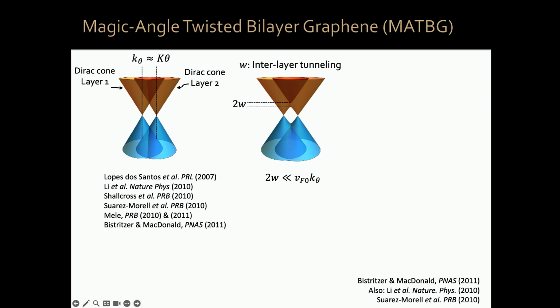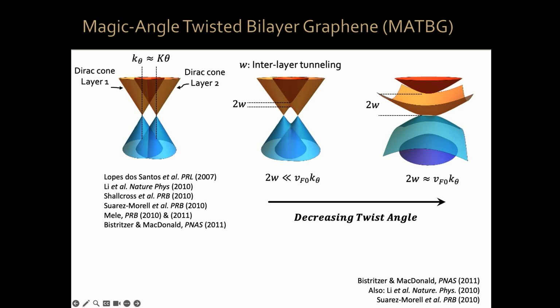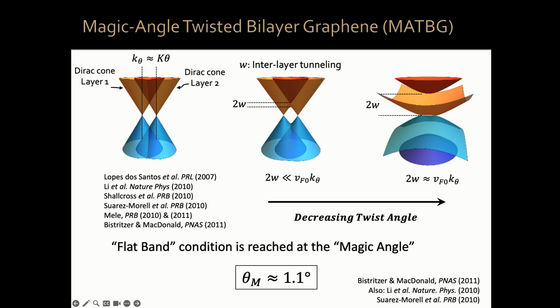If I now continue decreasing the twist angle, my Dirac cones come closer and closer together. Remember, at 0, they're on top of each other. So they come closer and closer, and this band gets pushed down, down, down, until there is an angle for which a flat band condition is realized. That band gets pushed down all the way to 0. That flat band condition is reached at an angle called the magic angle, and it happens to be 1.1 degrees for graphene on top of graphene. It depends on that interlayer tunneling.